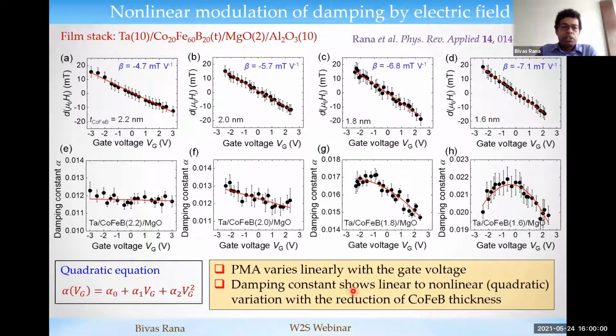So now coming to the result. For thicker film, we observe the damping constant varies linearly as a function of gate voltage, and as we increase the thickness, this variation becomes almost zero. For lower thickness, instead of linear variation, we get a nonlinear variation. We could nicely fit this nonlinear variation by a quadratic equation, where the damping can be expressed as something like this. Okay.